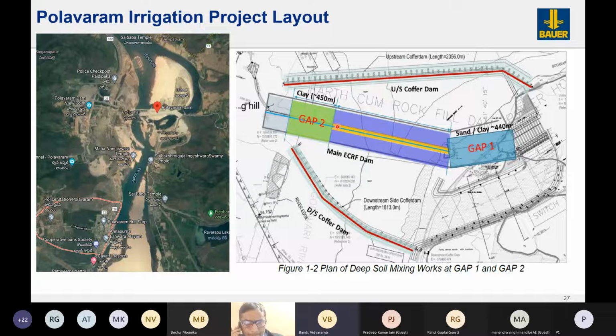What you see is a plastic concrete cutoff wall, and it also has limited strength. But the river is on the downstream side, on the basin of the river Godavari. The scouring depths are very high, and the chances of damage to the plastic concrete cutoff wall are significantly high. So in order to ensure that this cutoff wall is properly protected, and the impact of the scouring or the flood underwater current of the river is minimized, we are installing the DSM columns and also parallelly doing stone columns all along the width of the dam.